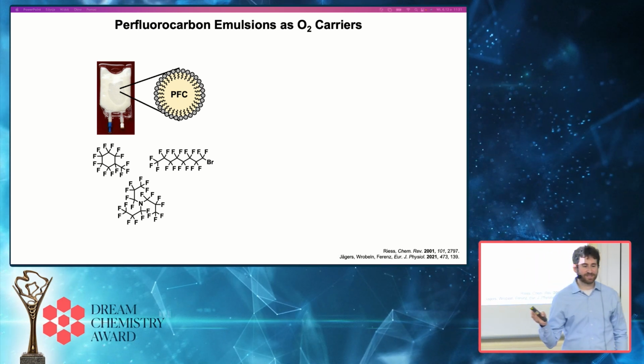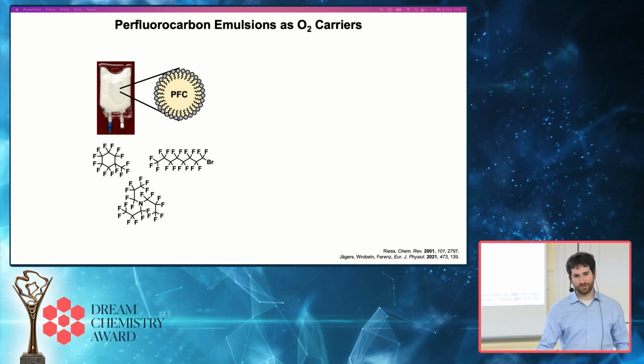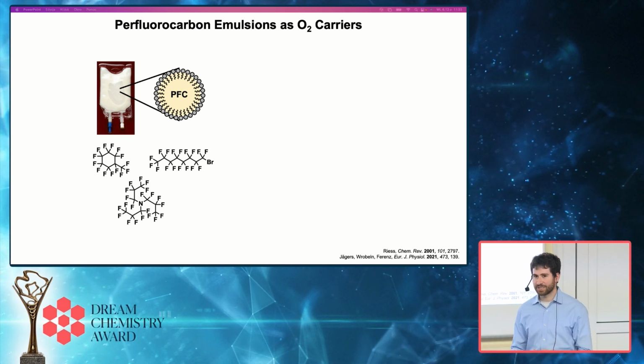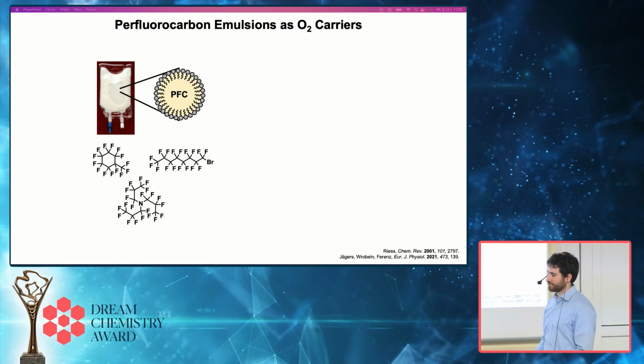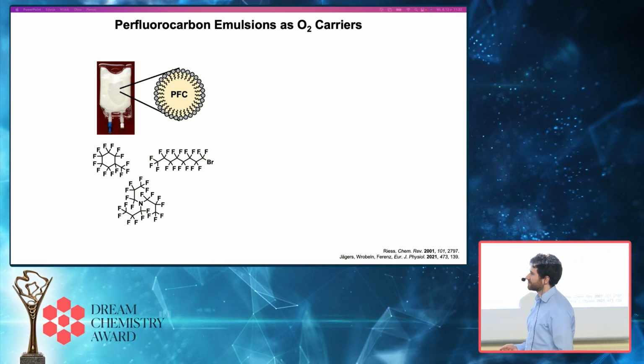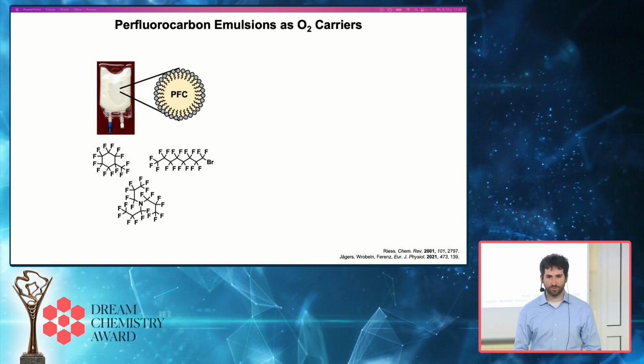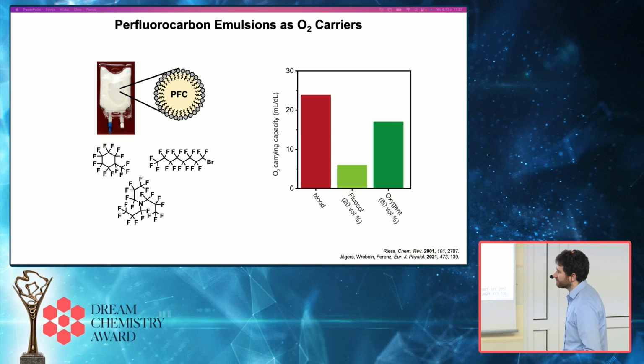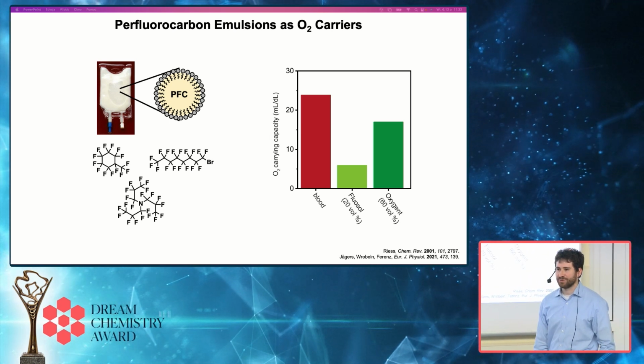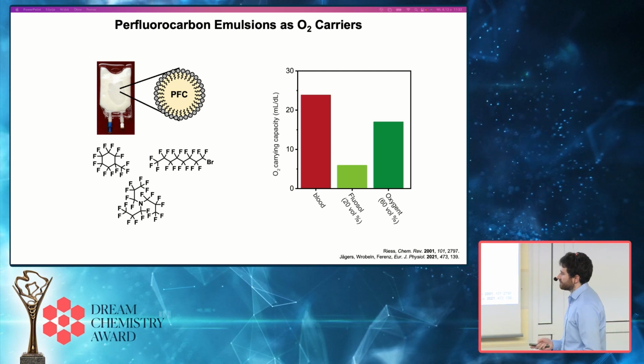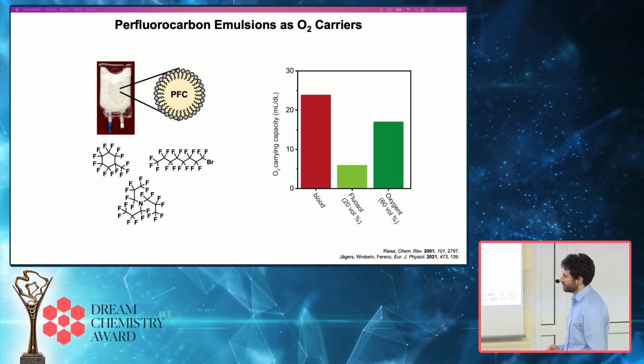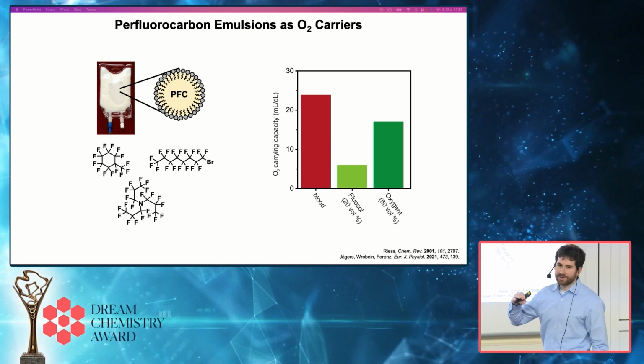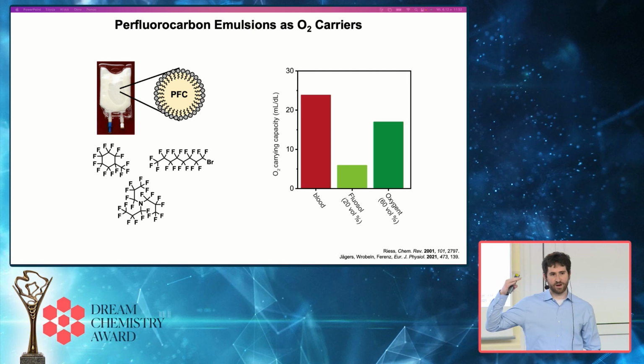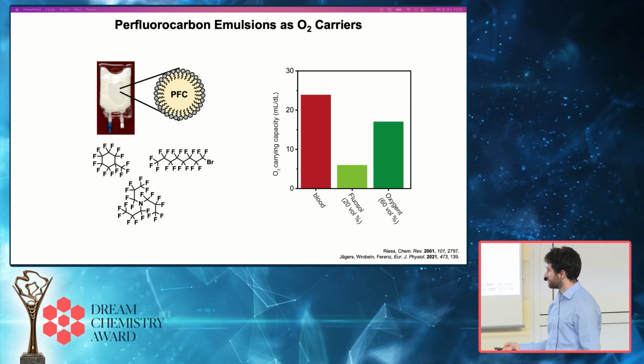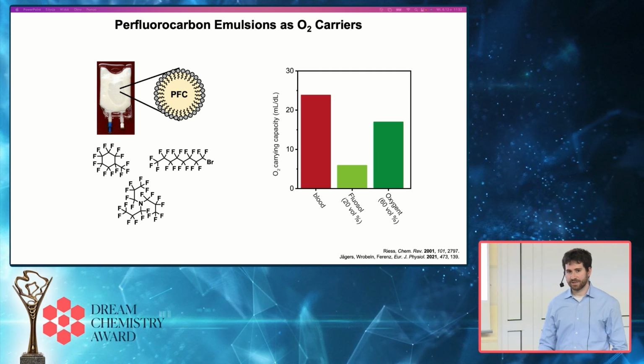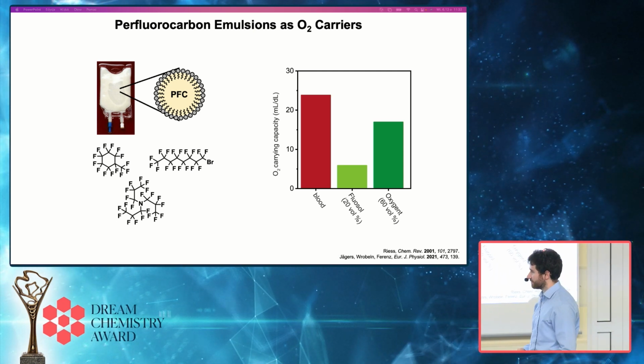So as an artificial blood substitute, one doesn't use a neat perfluorocarbon, but one takes droplets of perfluorocarbon liquids, coats them in some sort of surfactant because they're not inherently miscible with water, so things like a phospholipid or even different types of proteins, to form generally micron-sized droplets of perfluorocarbon liquids that are dispersed within water to form these kinds of emulsions. So still, though, even though these solvents have much higher oxygen solubilities than water, the amount of oxygen that you can actually store even at relatively high concentrations of perfluorocarbon, over 60 volume%, is relatively modest, and it's very hard to make a perfluorocarbon emulsion that has the same oxygen carrying capacity as blood. These are two commercial perfluorocarbon emulsions that have gone through clinical trials for a wide variety of different kinds of oxygen delivery applications.